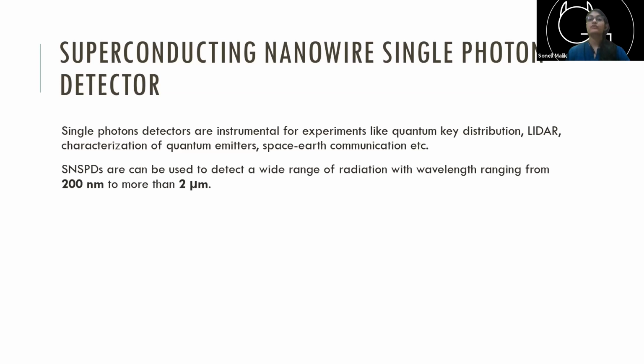SNSPDs can be used to detect a wide range of radiation. The wavelength of the photon can range from 200 nanometers to 2 micrometers, which is in itself a pretty wide range of photons to detect. Most single photon detectors, if they start with nanometers, can only detect up to, say, a few thousand nanometers. Then there are other single photon detectors that measure for higher wavelength photons. So one advantage of SNSPDs is that they have a pretty high range.